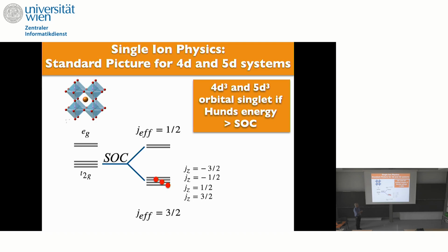We were imagining that these systems would be very good realizations of Heisenberg magnetism on an FCC lattice. That's why we were trying to study them first, and we had expectations for what would happen in that case. We would expect magnetic dipole order for the spin moments, pretty big spin moments because you've got 3 electrons, and nice spin waves with Goldstone modes. So we had well-defined expectations for what we were going to find, and a lot of those actually were realized.